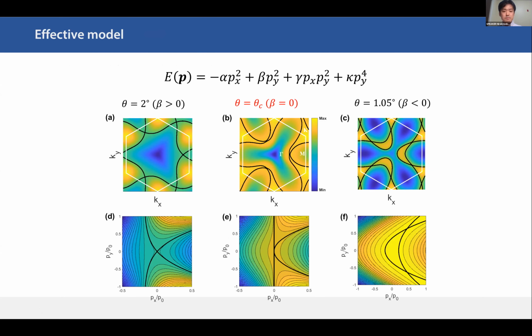So let me simplify the Fermi surface topology by looking at this Van Hove point. We can write down the effective model around the Van Hove point based on the symmetry at this point. For a larger twist angle, we see a single cross. For a small twist angle, we see two crosses and one energy maximum. And at the critical angle, we see a tangential touch of two Fermi surfaces.